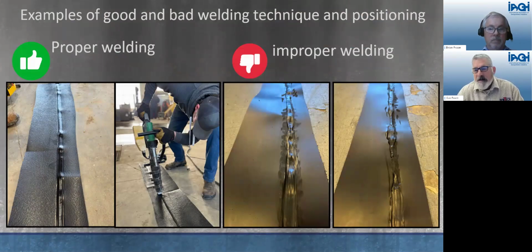Next slide, please. Examples of good and bad welding technique and positioning. There's a few pictures here illustrating proper and improper welding techniques. On the very left-hand side, you can see a nice, clean, straight weld, no grinding marks showing, centered on the seam. That's what we're looking for, a proper weld or a trial weld. The next picture just demonstrates proper welding position. The technician is in good stance. He has the machine centered on the seam, proper grinding techniques. That's proper right there.